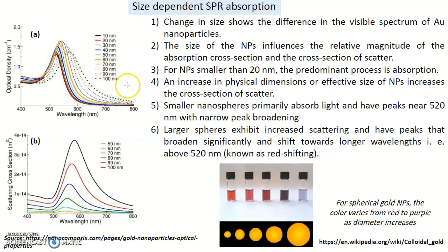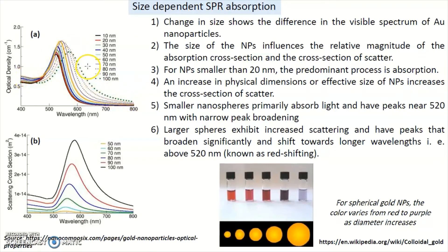For 80, 90, and 100 nanometer gold nanoparticles, the plasmon resonance wavelength is also shifted. In the range of 10 to 50 nanometers it is not that sensitive, but at 100 nanometers the spectra which was narrow becomes broad and its intensity also goes down. This shows how light interacts differently with different sizes of metal nanoparticles.